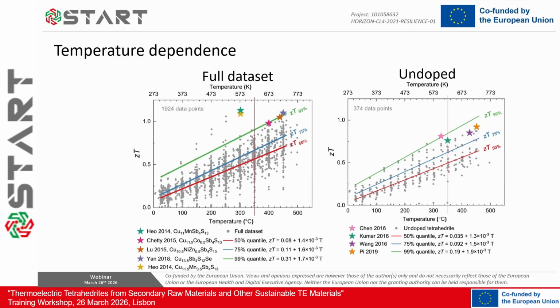So maybe we shouldn't use the 50% to define the representative behavior of the tetrahedrites, but rather the 75%. This is something we are trying to propose. If you want a benchmark, is our material better than the others? Should we compare it to the average? Should we compare it to the maximum?